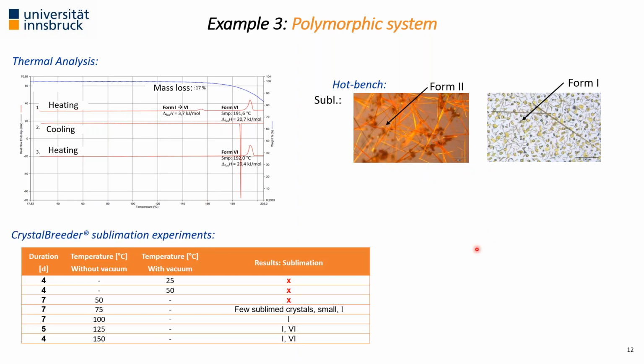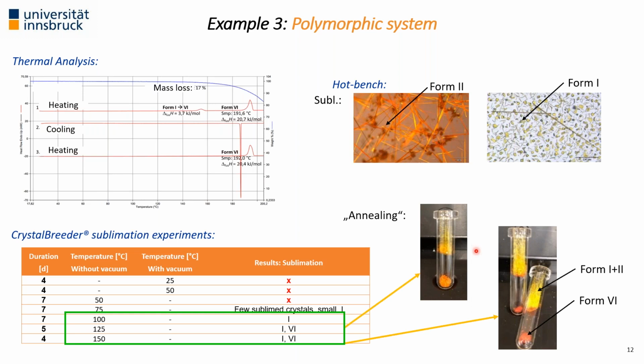So with the crystal breeder, what we've done is fill our compound once again into those vials and increase the temperature to predefined values, with or without reducing the pressure, and at lower temperature, no sublimation occurred within up to 1 week. When we went to higher temperatures, here we didn't use reduced pressure because the compound was colored, and this would have caused a color change of the tubes and everything.